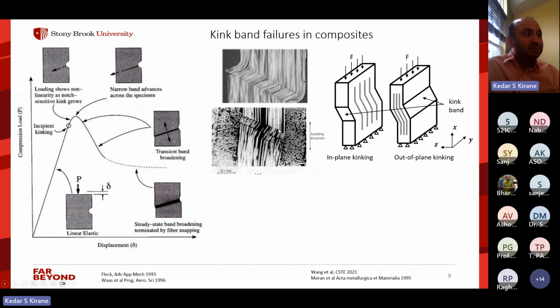Now, the strength at which this happens, the compressive strength, is usually lower than the tensile strength. But the compressive failure also has this prolonged plateau, so it can actually dissipate a lot of energy by compressive failure also. Now, physically speaking, what happens during this phase is that this band becomes broad. It broadens, and it is a quasi-plastic process.